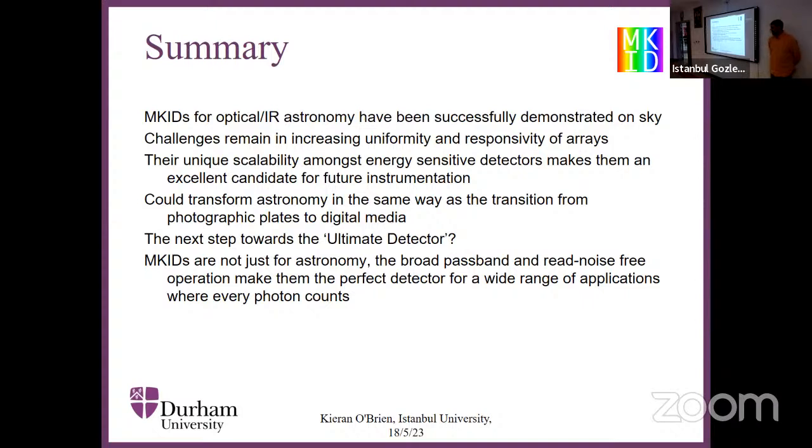The material, titanium nitride, was chosen because you can change the stoichiometry of the material, the nitrogen content, and you can tune the critical temperature. It's typically about 4 Kelvin, but you can tune it by reducing the nitrogen rate to be around 900 millikelvin. What we want to do is operate around 8 times lower than the critical temperature, to avoid thermally generated quasiparticles breaking Cooper pairs thermally.